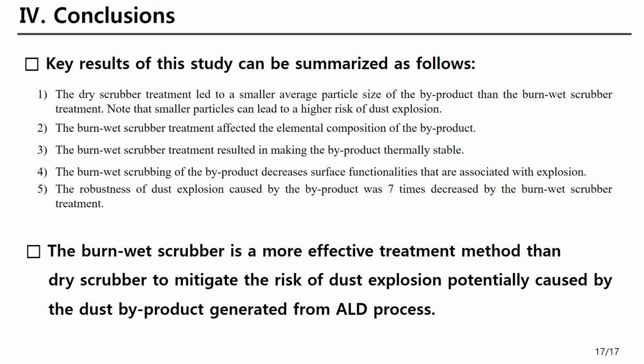As a result, the key results of this study can be summarized as follows. First, the dry scrubber treatment led to a smaller average particle size of the byproduct than the burn-wet scrubber treatment. Note that smaller particles can lead to a higher risk of dust explosion. Second, the burn-wet scrubber treatment affected the elemental composition of the byproduct. Third, the burn-wet scrubber treatment resulted in making the byproduct thermally stable. Fourth, the burn-wet scrubbing of the byproduct decreased surface functionalities that are associated with explosion. Finally, the robustness of dust explosion caused by the byproduct was 7 times decreased by the burn-wet scrubber treatment.